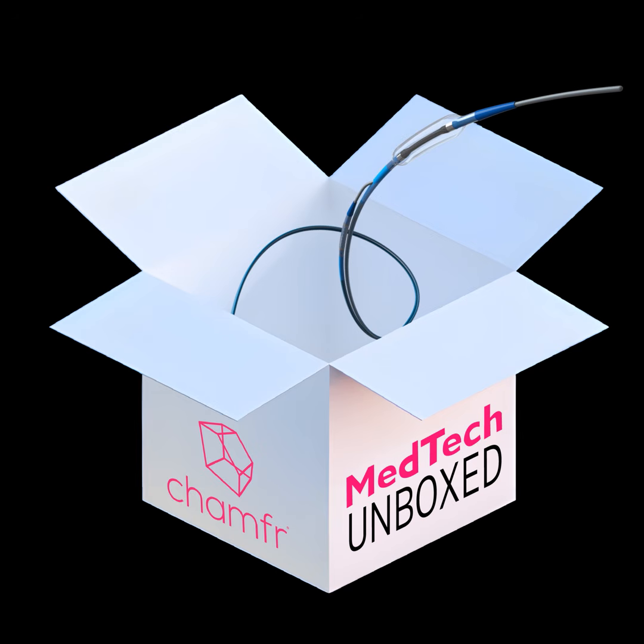There's certainly, as you alluded to, where PTFE really shines, whether it's the film cast, which you can get down to half a thou, or the extrusion where you can get 7.5 tenths, thousandths of an inch. It's kind of hard to beat it in that respect. But not all catheters require that ultra thin wall thickness. So there's certainly a place for these thermoplastic liner technologies.